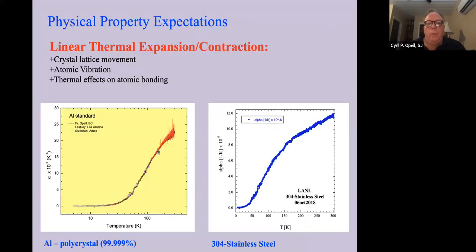Now, finally, linear thermal expansion and contraction. This has to do with the bonding of the atoms and the crystal lattice movement. I give you an example of a well-behaved material like aluminum, which is a standard. On the left there is a sample of very pure polycrystalline aluminum, and three different people measured it, and it comes out the same.